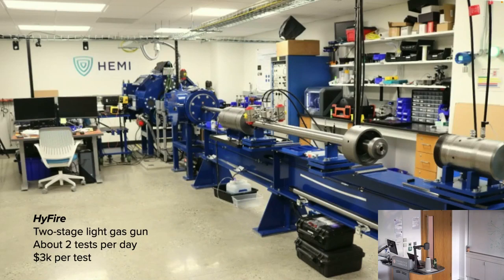As you can see, just based on the scale of this, you can imagine that these experiments are difficult and time-consuming to set up. If we do 2 tests per day, 1 in the morning, 1 in the afternoon, we're doing pretty well. And given the cost of the consumables and the time and everything that goes in, each test costs us about $3,000. So if you're trying to train an ML or an AI model for some sort of Gaussian process regression or something like that, where you need many, many data points, this kind of experiment is both too slow and too expensive to be